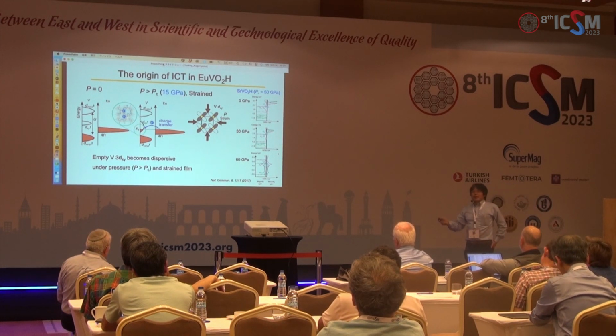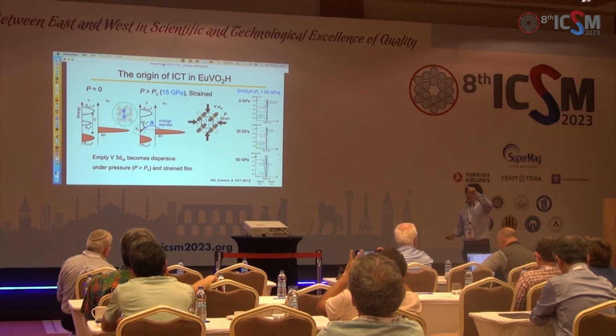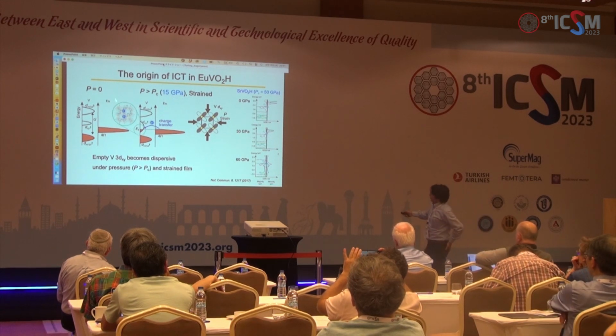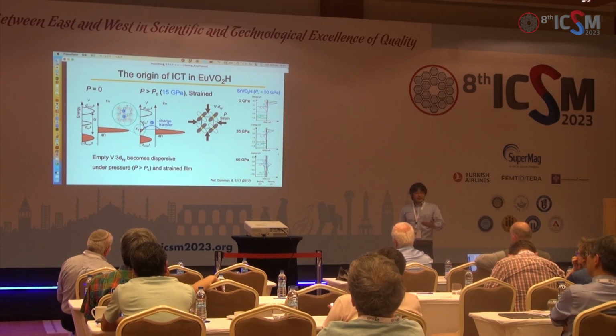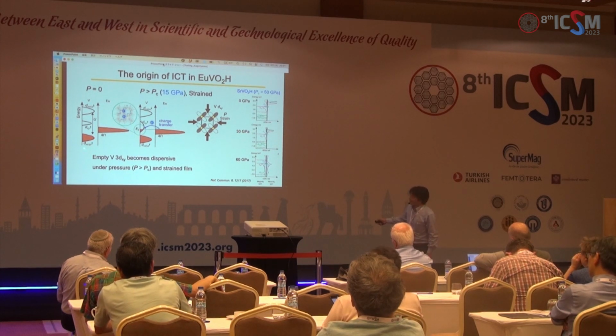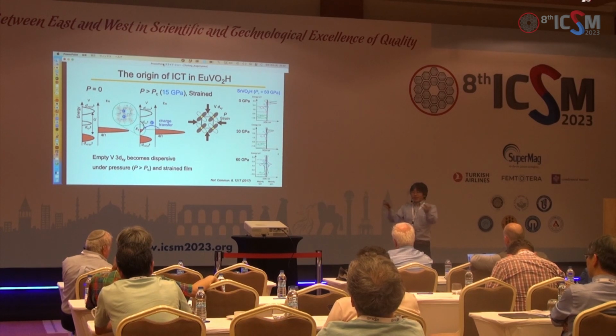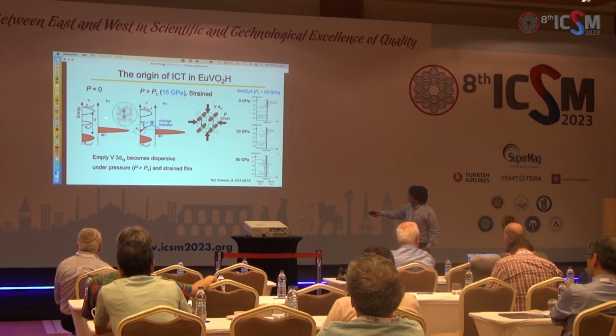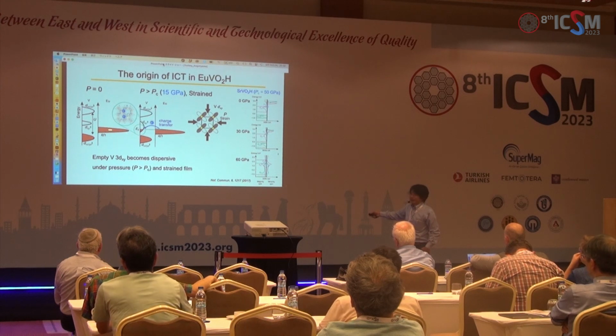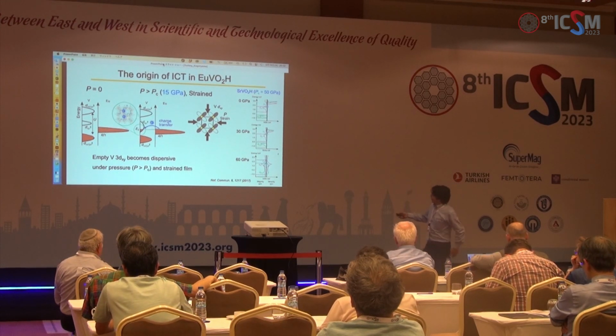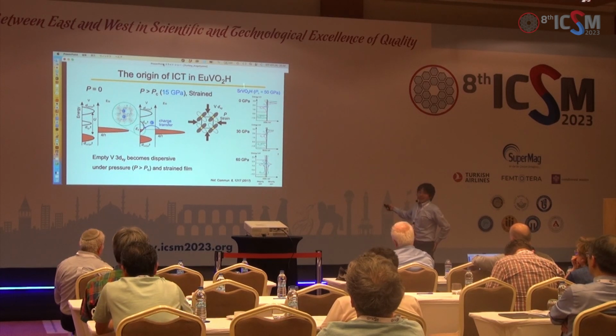So at zero ambient pressure, or maybe powder sample, as I mentioned, the Eu takes 2+, vanadium takes 3+. So at room temperature, the vanadium is insulating, orbital-insulating, so there is the splitting of the xz and yz orbitals. So now it's a half-filled state. So there are 2 electrons in these 2 orbitals. And because of the repulsive interactions, that one is split based on the U values. And the Eu 4f state should be located somewhere here. Okay. This is the electronic state expected for this material at ambient pressure or ambient conditions.